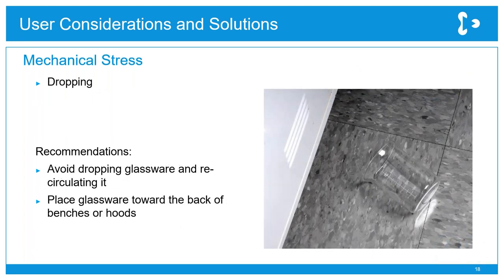And dropping is a really obvious problem with glassware. It may break or it may not break, but even if it doesn't break, it may be damaged and it may fail later down the line. So we recommend that if you do drop glassware, you actually dispose of it and you don't use it any further, even if it doesn't break.